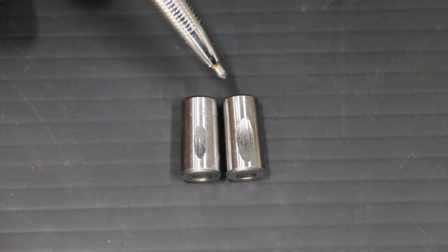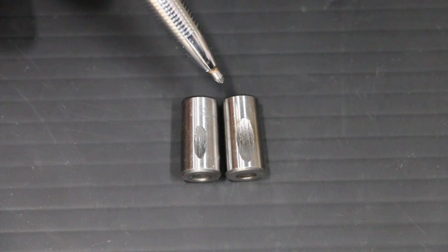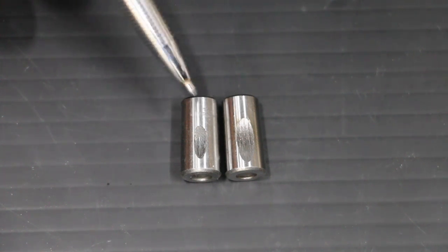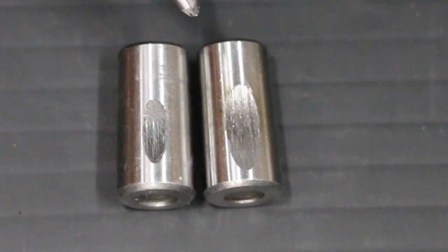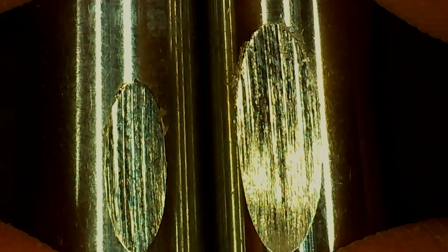Mag 1 is on the left and the vintage grease is on the right. There is a lot of damage to that vintage grease bearing. Even Mag 1 had quite a bit of damage, but this is by far the most damage I've seen to a bearing on the lubricity test. This vintage grease just doesn't offer very good wear protection.